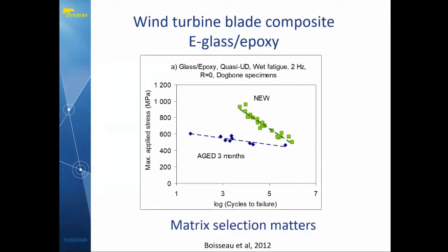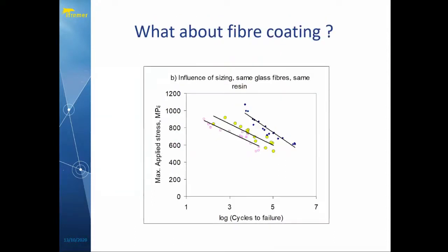So matrix selection matters. We have other materials which we've tested with exactly the same fibers, but with a different resin, where the aged curve saturated was on exactly the same curve as the new dry material. But the bottom line is, one of the first parameters you need to look at is what matrix you're going to use, as the matrix which are used in wind turbine blades are not necessarily the matrix to use in a tidal turbine. Next slide, please.